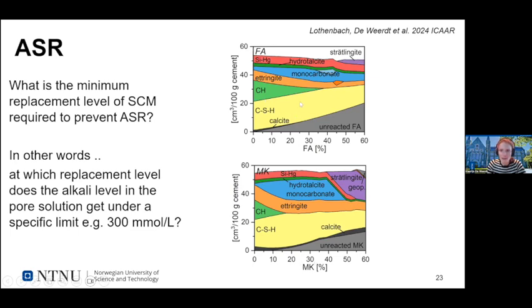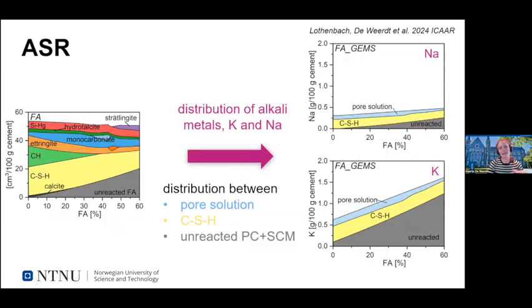And when we look at the hydration phases, you can see that the pozzolanic reaction of fly ash and metakaolin leads to the consumption of your Portlandite, as we've seen earlier with the calcined clay. And then you get more CSH and more AFM. You can see this even clearer for the metakaolin. And also note that we put a limit to the reaction degree of the fly ash and the metakaolin, and that's actually based on one of the figures Ruben showed in his talk. So here we have the phase assemblages and how it changes with the replacement level. But what we're actually after is how does that affect the alkali distribution? We know that sodium and potassium will distribute between the pore solution, CSH, and the unreacted Portland cement and SCM.